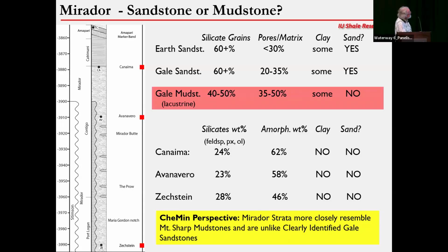There are usually a little bit of clays in there, and there's always sand grains visible. In the Gale mudstones, on the other hand, there's always a significantly low amount of silicate grains, which are silt size, and we have the amorphous matrix plus minor phases, about 1/3 to half. There's a distinct difference between the sandstones on Earth and Gale versus Gale mudstones.